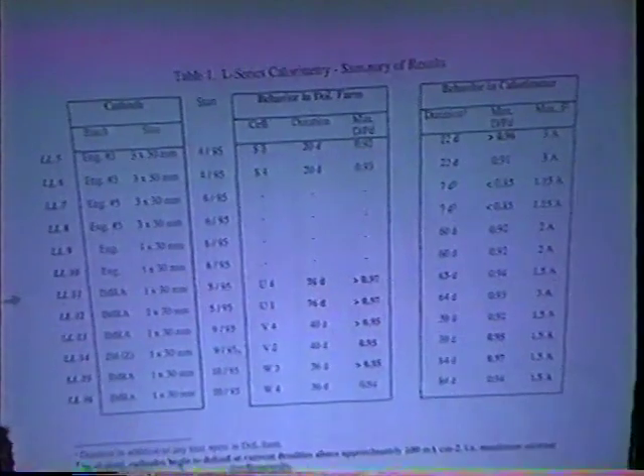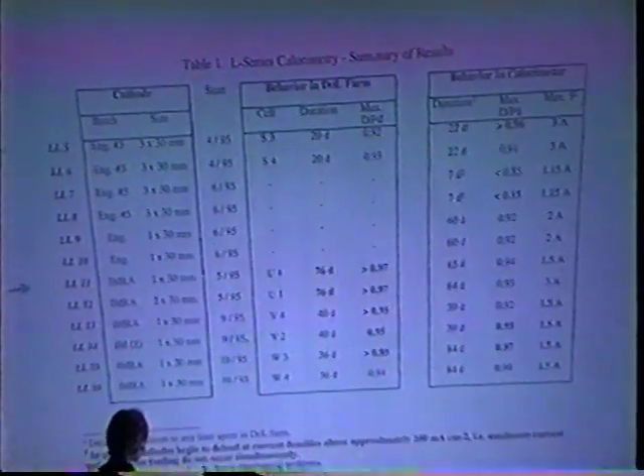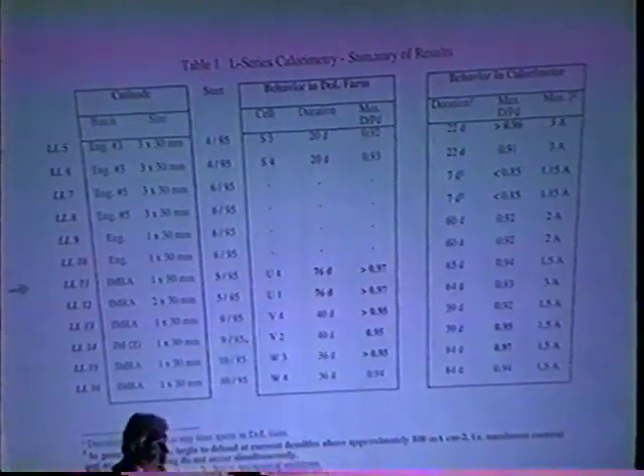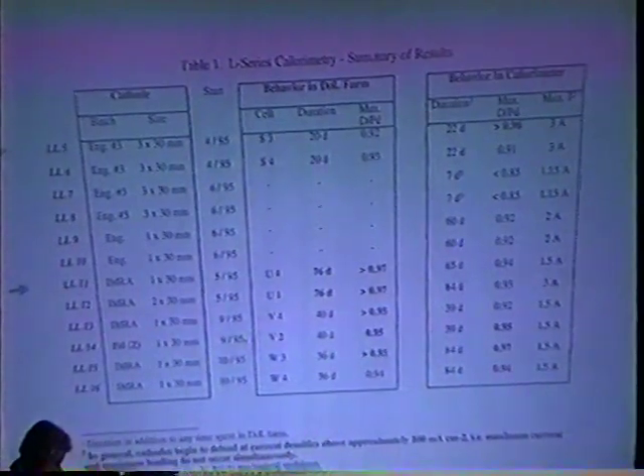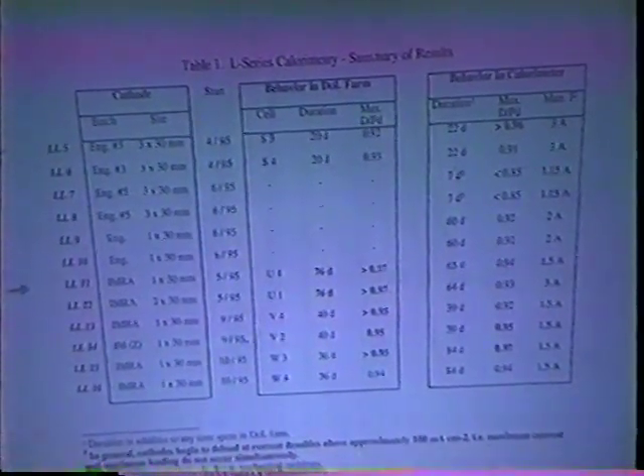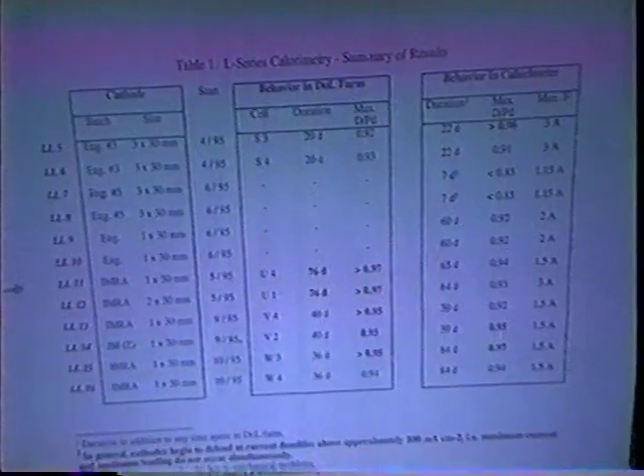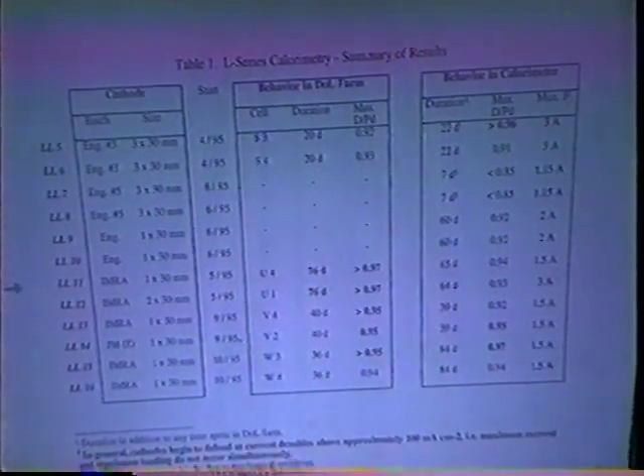As you can see from this graph, we've obtained very good loadings in some of our experiments, greater than 0.97. We've achieved those loadings, we've achieved high currents. We've obviously had durations. These are in days. We've run experiments for 84 days.